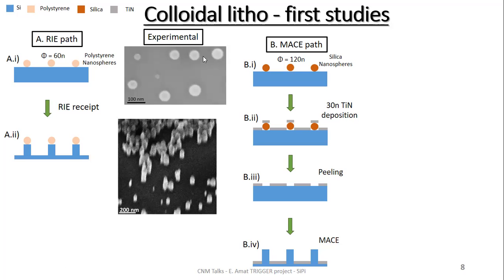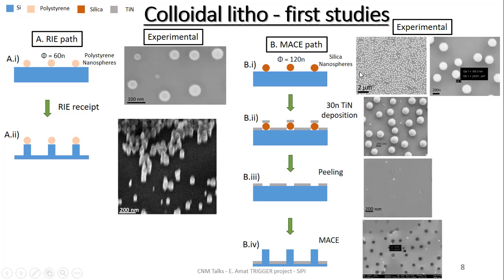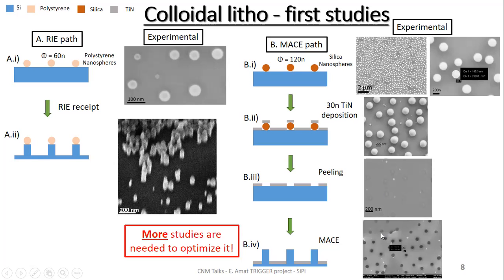We have properly deposited the nanospheres, 60 nanometer nanospheres, and we obtained the first pillar. We can say that this is a pillar, but it should be significantly optimized. This is tilted 45 degrees, just to see the pillars. For the MACE path, we metallize the nanospheres, we make the peeling, and we make the first proof, the first attempt at MACE. But more studies should be done to optimize.